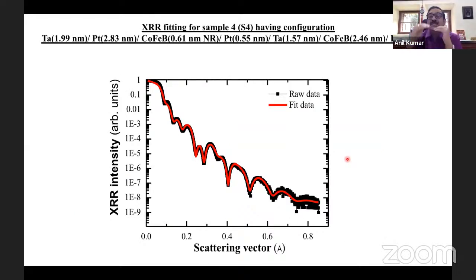Now, when I talk about this multi-layer structures, we intend to deposit a particular thickness. Then, generally we do very periodic calibration to make sure that we have the exact thicknesses. But in spite of that, we still verify the thickness of each film that we deposit by X-ray reflectivity. So this is the X-ray reflectivity data, and this is the fitted curve. From the fitted curve, I can get the thickness. I wanted to put 2 nanometers of tantalum.